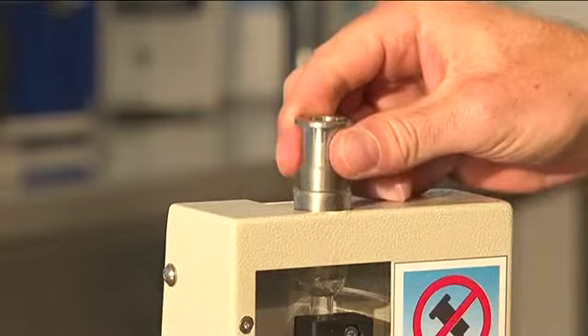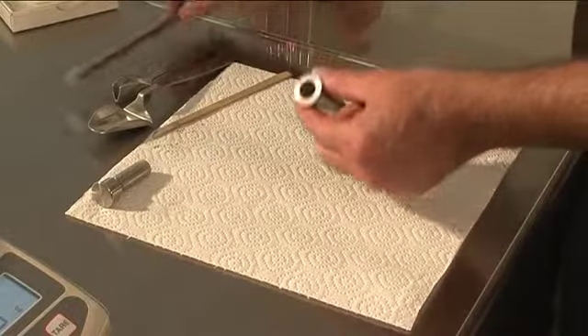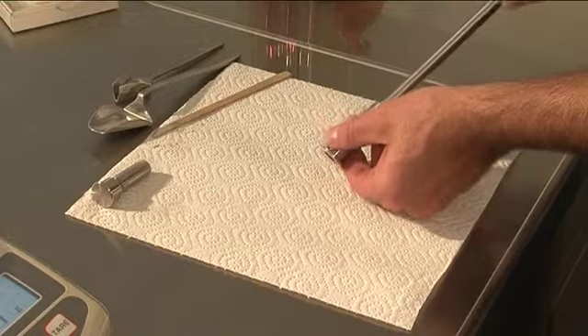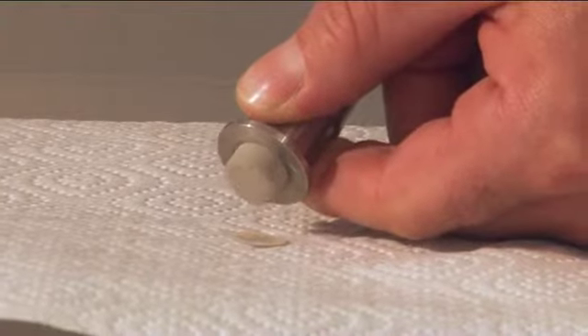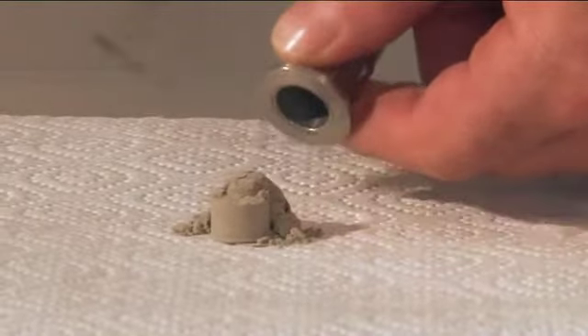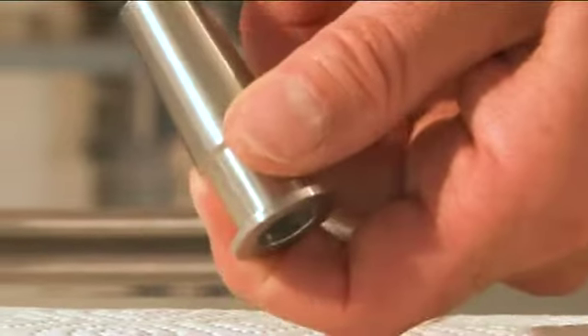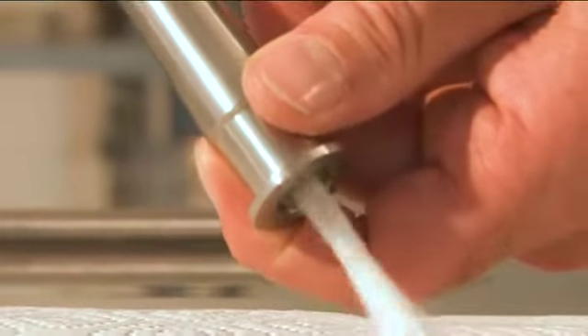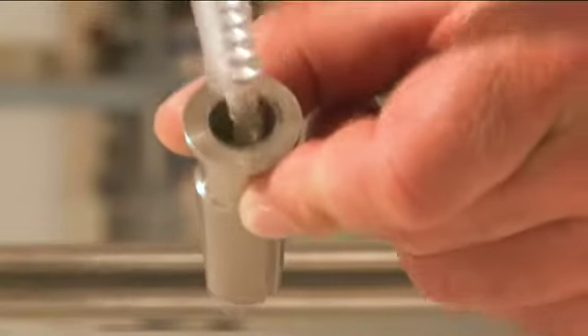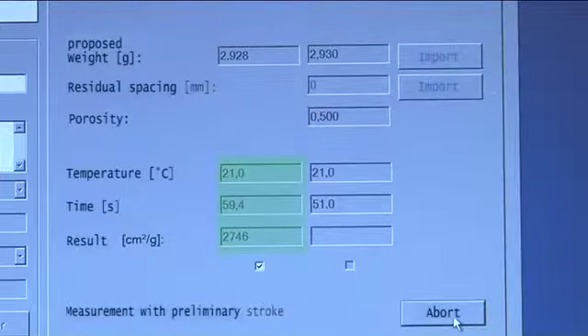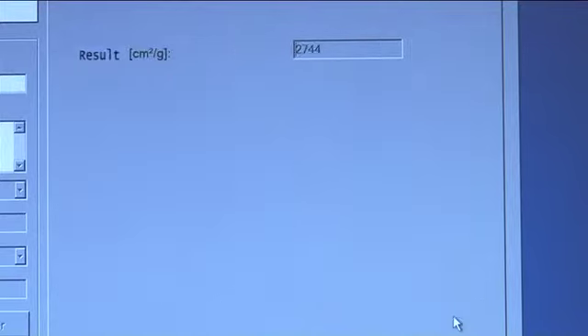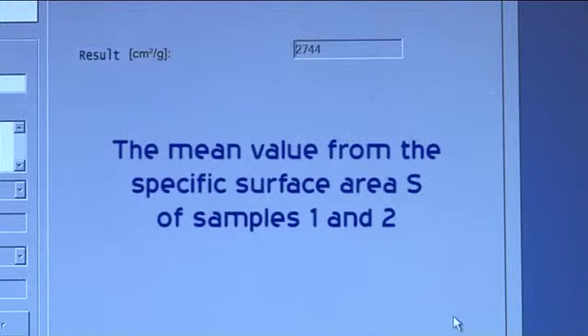Remove the measuring cell. From below, the cement bed is pushed out of the cell. The cell is cleaned and prepared for the second cement sample. A first and second run on the second sample are performed. Afterwards, the mean value from all 4 measurements is compared with the Blaine value of the cement sample. The result is rounded off to the nearest 10 square centimeters per gram.